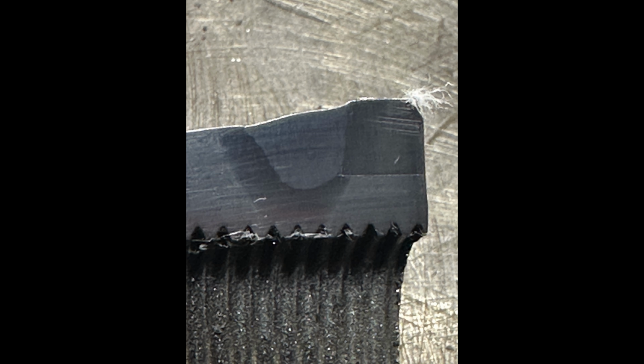What really bothers me the most about wire welding in general is that when you visually look at these two welds next to each other, they literally look almost the same at surface value. Like if you put a coat of paint on them, you'd have no idea that you have a weld like this that's perfect and good, and then the other weld, which looks just the same, that has a lot less fusion. And that's the issue to me with wire, is that visually you cannot tell what the internal of the weld looks like. With stick and TIG, it's far easier to know what's inside.